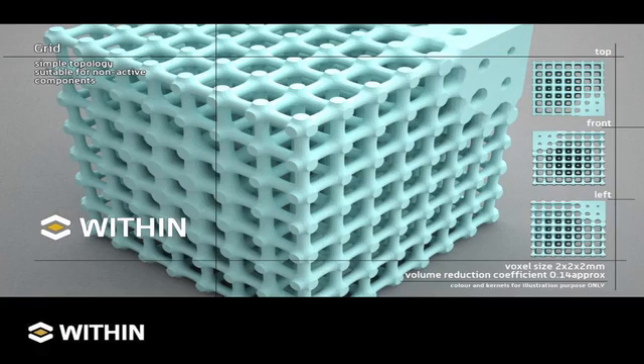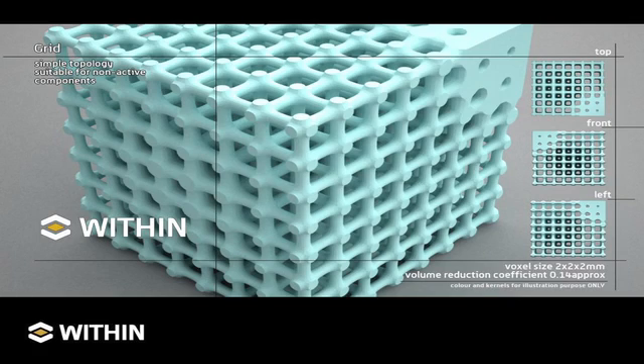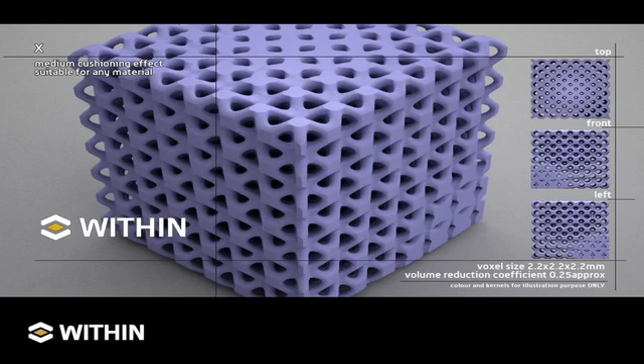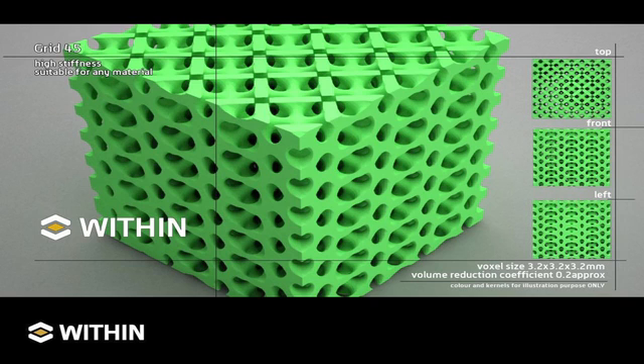This part here is called a grid topology. You can see it has a very grid-type structure, but we can vary the density from being almost solid in one corner, smoothly gradiating to becoming more porous. We have a value called a volume reduction coefficient, which for this component is 0.14 — meaning this object is now only 14% of the weight or material of the original product. We have a wide range of these lattice structures that can populate a solid volume, whether for light-weighting or osteointegration.